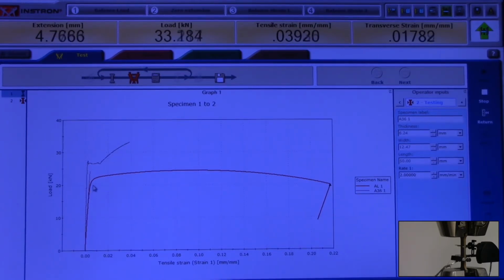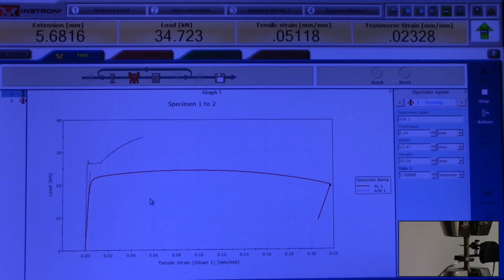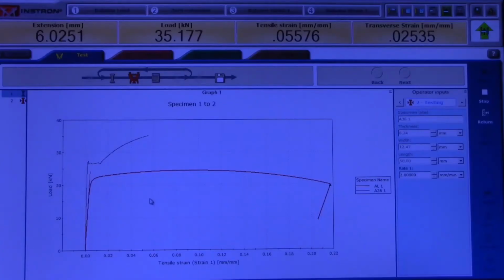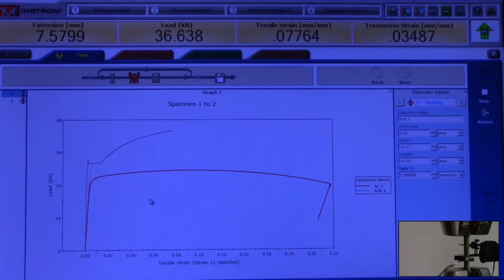The aluminum, once we yielded, the load didn't really increase very much. But with the steel, you can see that it's still increasing quite a ways. And like the aluminum, we won't see much action in our specimen until we've reached the maximum load and start to neck. So our load is still slowly increasing. We haven't leveled off yet.